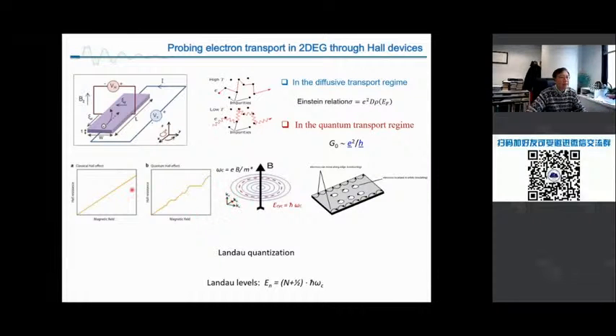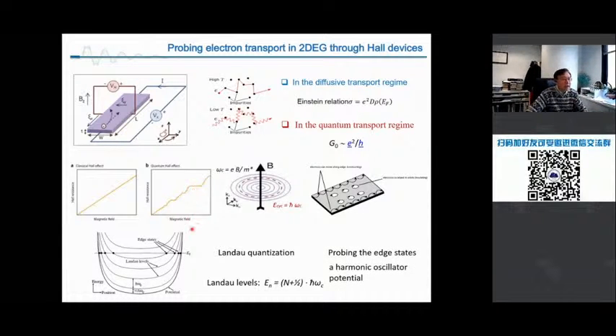In the traditional classical Hall effect, as you increase the magnetic field, the Hall voltage that you measure across the sample increases linearly. The quantum phenomenon shows plateaus. Those plateaus represent the so-called Landau levels. Those high-speed electrons inside your 2D material, when you apply a magnetic field, undergo cyclotron motion. We use a harmonic oscillator to describe this phenomenon. So electrons occupy different energy states, called Landau levels.